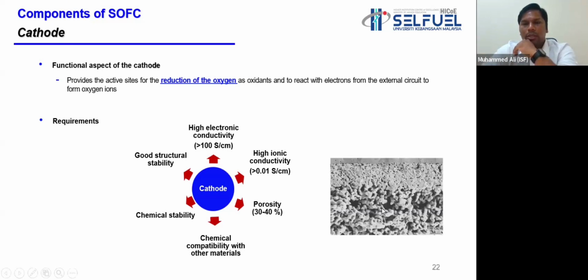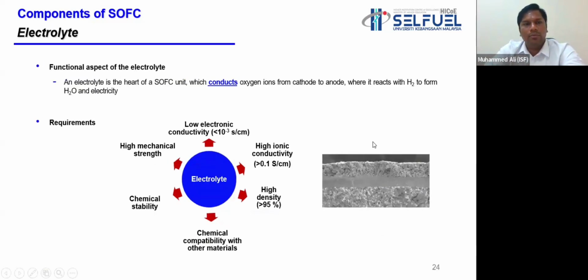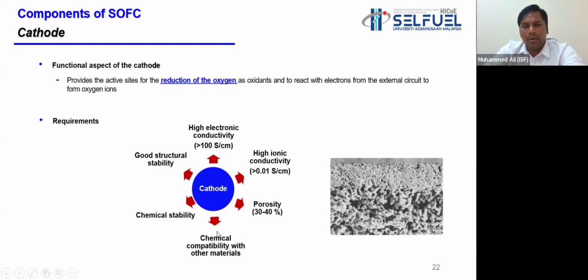You can see from the micrograph that I have shown some porosity, right? So it should be nearly 30 to 40% porosity, and it should be chemically compatible with other materials, because we are talking about a sandwich structure, right? Electrolyte and anode and cathode. So if there is any chemical reaction at this surface, we'll have delaminations. So mechanically it will fail. So to avoid that, it should be chemically compatible.